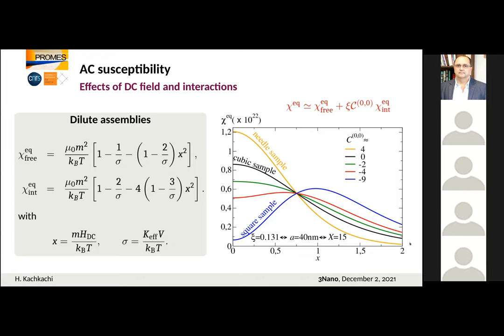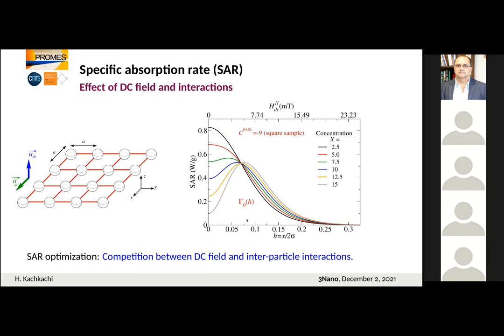And this, we will see in a bit, is very important, because if we now compute the SAR, which is the specific absorption rate, we see the behavior of the SAR as a function of the magnetic field for different concentrations this time. X is 1 over the separation to the power 3. For example, when X is 10, A is 46 nanometers. A is the edge-to-edge separation.